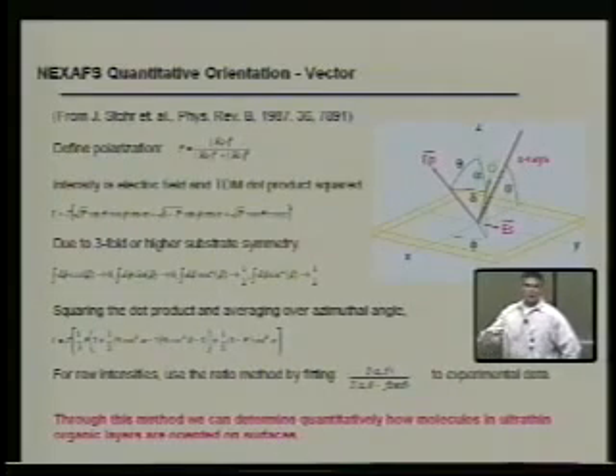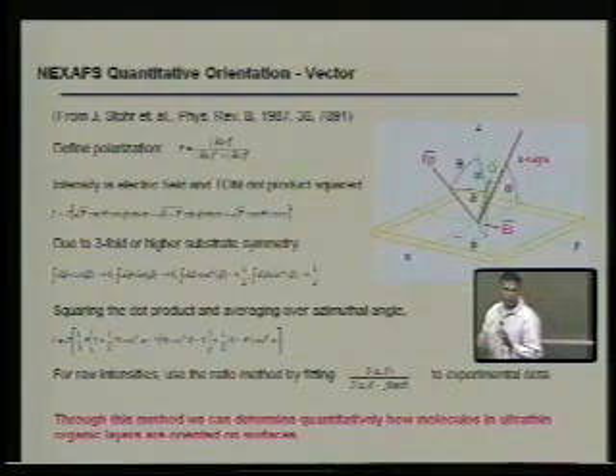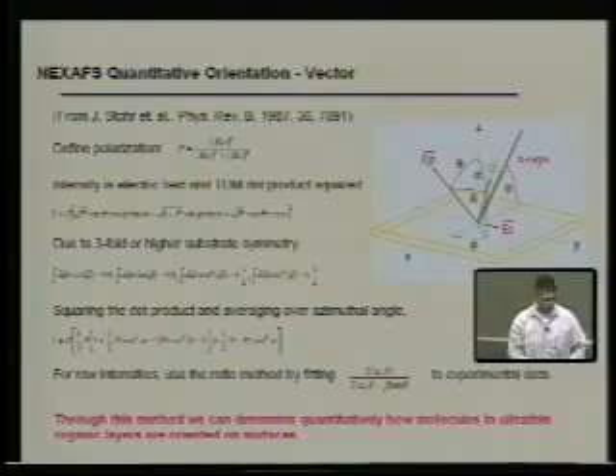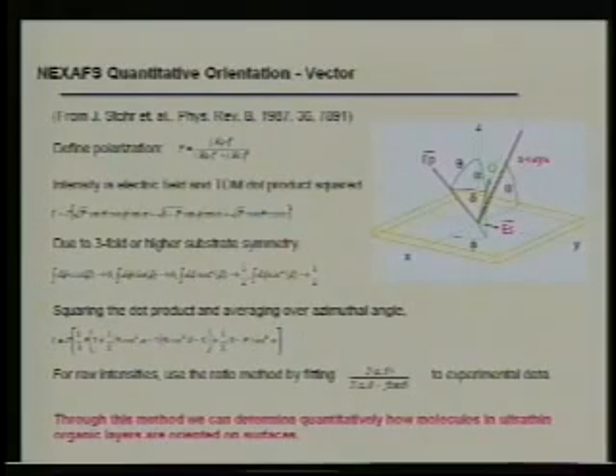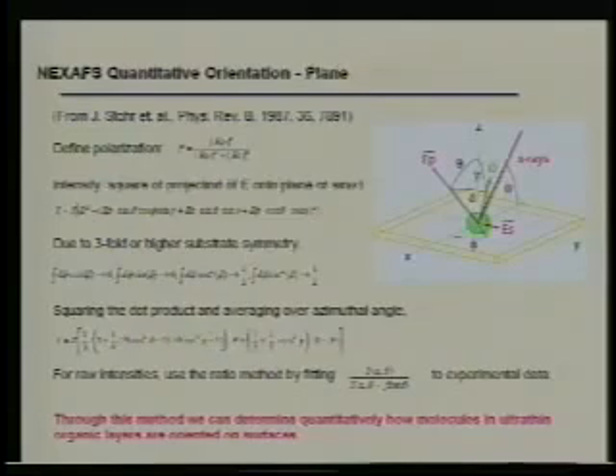And what you can do is take the different spectra here, where you're actually changing theta. So at 20 degrees you have one term, and then you change your theta, keeping the other fixed, and you take the intensity difference between I at 20 and I at 30. You can actually get a value of cosine theta versus I. And this gives theta, that's the angle of the material on the surface. So this is for a vector on a surface. And if it's a plane, you have the same sort of idea here, but now you have a normalization, phi plane.